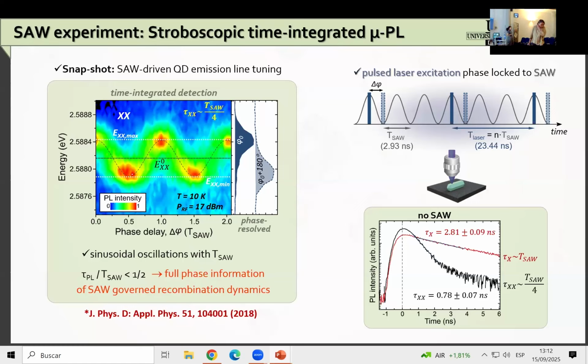At the end, you mentioned that some of the effects that you see when increasing power in the acoustic wave could be due to the rotation of the flake. Okay, is this a pure mechanical effect, or are there some thermal effects also because you are heating more? It's actually a reversible effect. It's a pure mechanical effect because we could see while doing the experiments that we have the splitting.